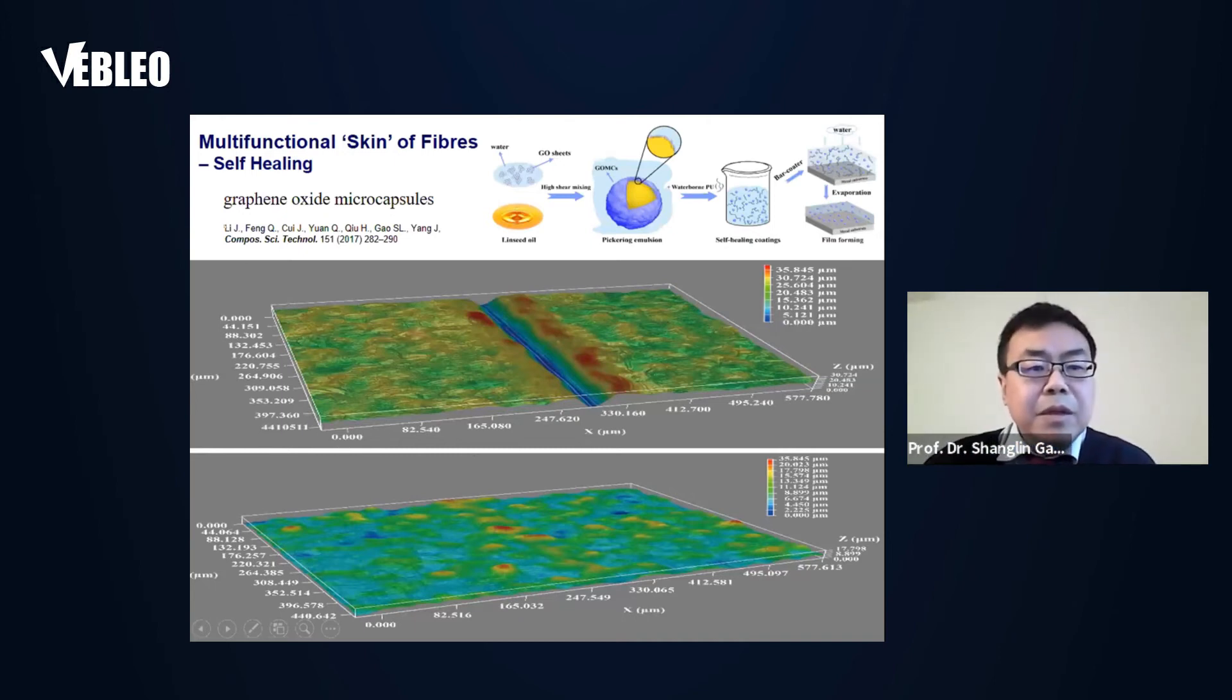So Professor Li Jun gave good work about developing graphene oxide. The microcapsules actually can make self-healing of these micro cracks. What he did was use the oil-water interface and then they grabbed these on the interface area. So we can make such micro cracks, and this graphene sizing has quite easy self-healing. When they crack, after one week you can see it's almost fully recovered. So this can give a longer service time for this composite.